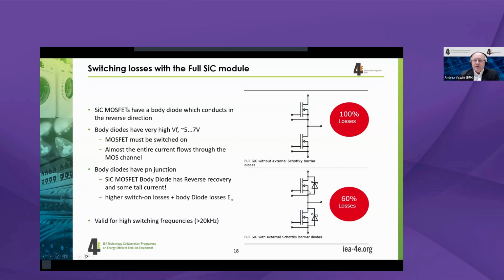The question here is, should you use full SiC without external SiC Schottky barrier diodes, or should you use additional SiC diodes, which is a cost criterion? But as you can see, the internal body diode in the SiC MOSFET has, first of all, a very high forward voltage. So it means that you have to switch on the silicon carbide MOSFETs and let them conduct in reverse. But what is more important, it still has a little bit of reverse current. So adding a very fast additional SiC diode here will reduce the losses. So while silicon carbide has very, very low switching losses, it's even better to have anti-parallel or freewheeling diodes also based on SiC to have even less losses.